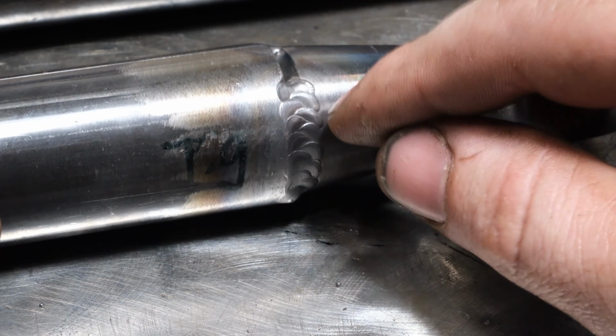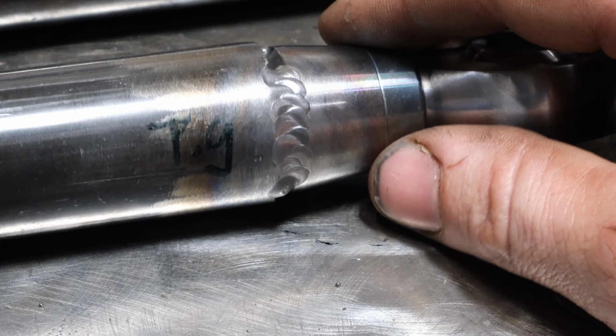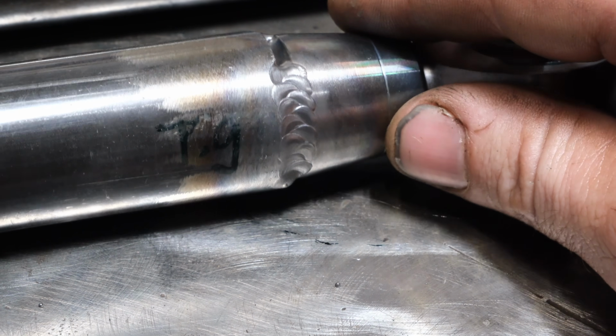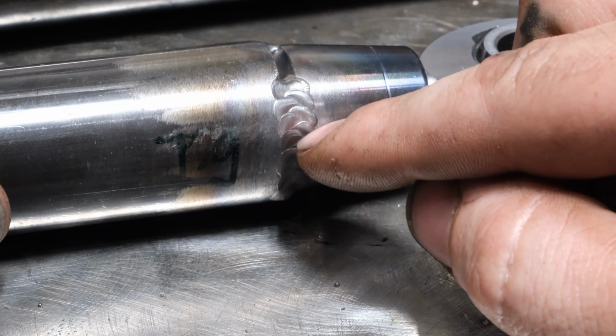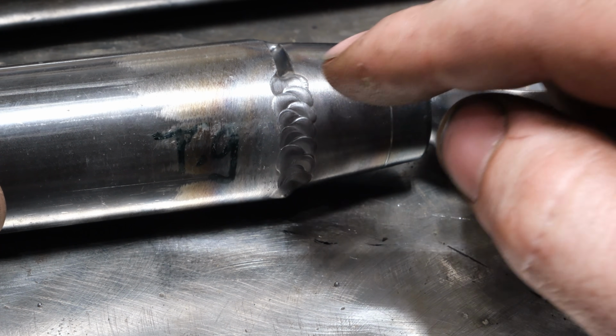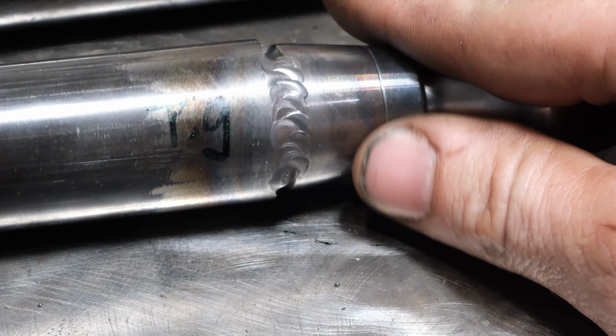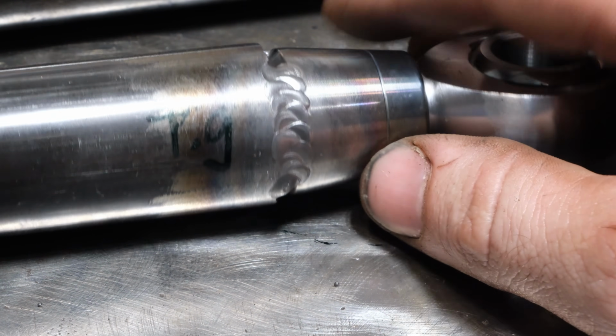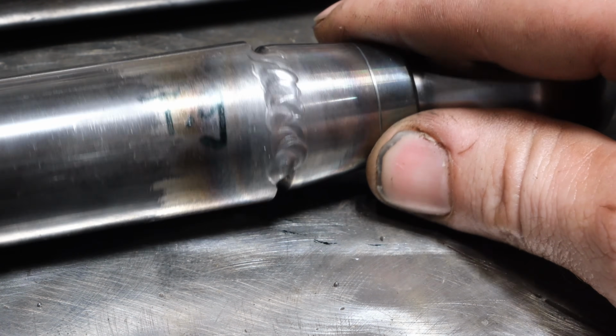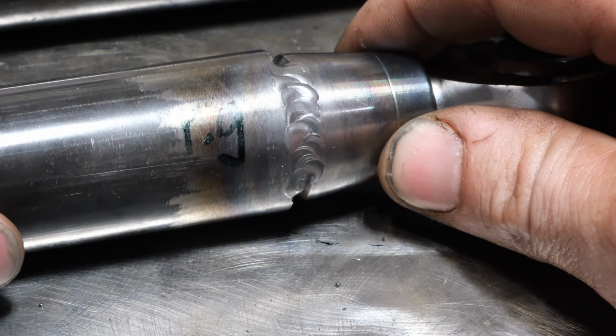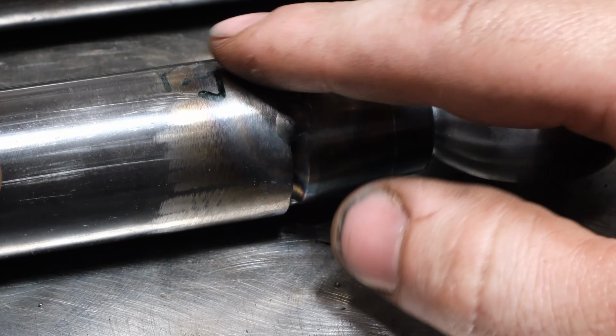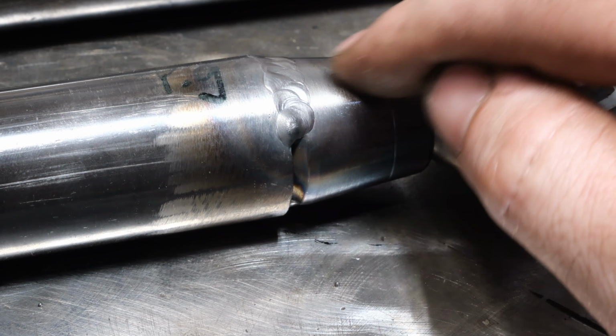Now, the two pass I did here, which is more of a replication of how I weld these, is a single pass with a tight arc on the first pass, and then I go over and weave it with a slight weave for a cap, and it's done in two passes. Now, when you look at that, not the greatest work, not the worst, but everything's nice and smooth.